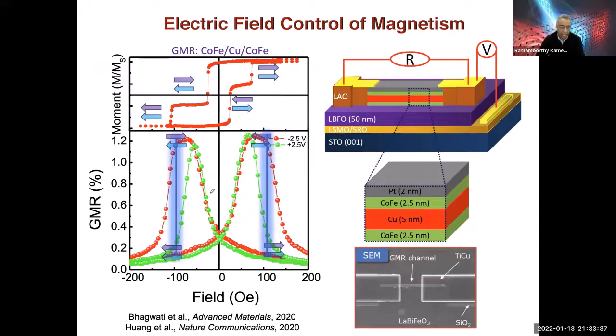Great question. I should have explained. All of this is from the cobalt iron, copper, cobalt iron stack. The LSMO is underneath the LBFO. If you remember, I said one of the issues is the work function. Strontium ruthenate, it turns out, which we didn't know until we did this whole piece of work, is forming a Schottky barrier to BFO. So we put LSMO just to manipulate the Schottky barrier. It's about 2 to 3 unit cells of LSMO on top of the strontium ruthenate. But all of the magnetic stuff is happening here.